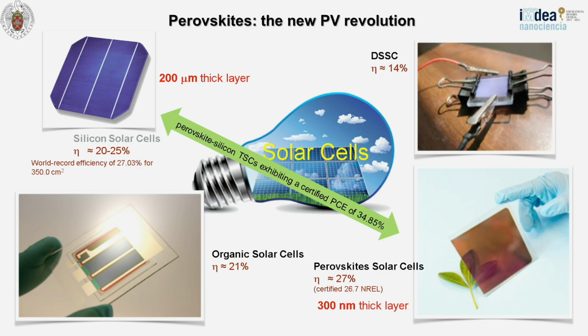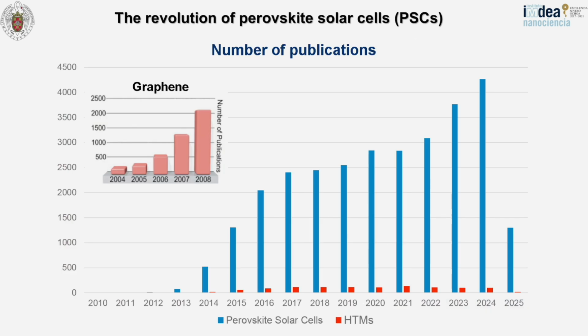Something of interest just to show you, if you take silicon solar cells, the thickness of the photoactive layer is roughly 200, 300 microns. But if you go to perovskite solar cells, the thickness is roughly the same number, something like 300 nanometers. That means 3 orders of magnitude less material than the other one. So this is to take into account.